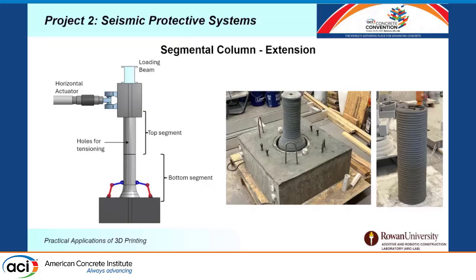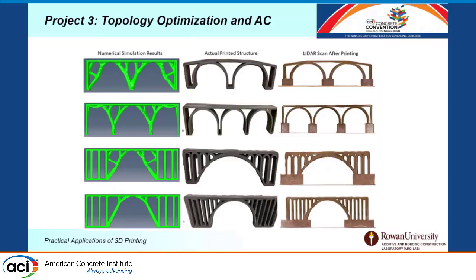We also can print segmentally and connect the segments with post-tensioning. And you can see here on the right side, we have a cavity for post-tension and a cavity for rebar to be grouted in process. As I mentioned, we also work on compression-only structures, which are designed to maximize compression forces and minimize tension. We didn't reinvent arches, but with 3D printing, we can come up with really nice designs for arches, which we did at Rowan, and on the right side we used LiDAR to scan and compare it to the original file.